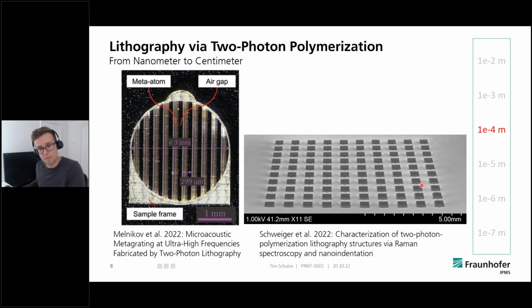And another thing I want to point out is this image here. So this is again a parameter sweep over different printing parameters, different printing laser intensities, and also scanning speeds. So whenever we build something, a laser scans through the structure to polymerize certain areas, and this scanning speed can also be addressed for parameter tuning. And here we are currently trying to establish a non-destructive testing process of our structures.